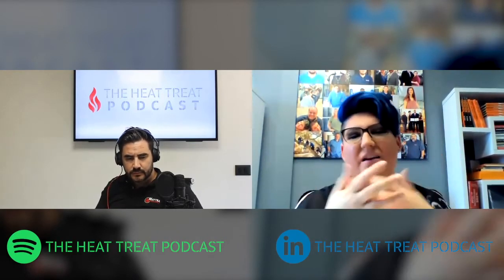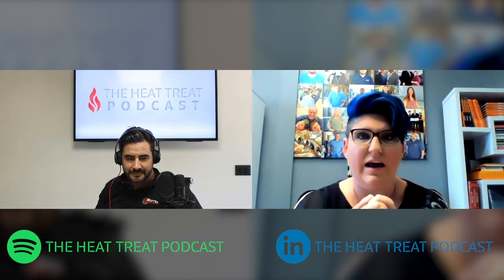So once you've equalized at those different set points, you're going to ramp up to your final set point. For brazing, you've got to watch out for the liquidus. You want to get in and out. The time at temp is typically very short, between 4 to 6 minutes, depending on part size. Spending time at liquidus when you're brazing will allow the alloy to flash out further through capillary action. We do not want the alloy to travel a whole lot. So once we hit that liquidus, quench it.